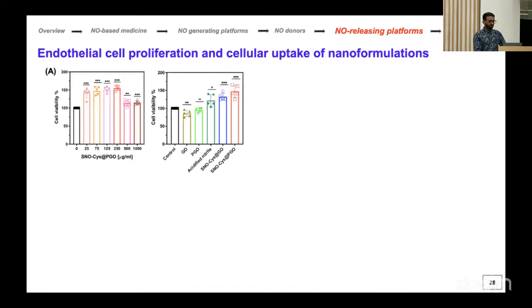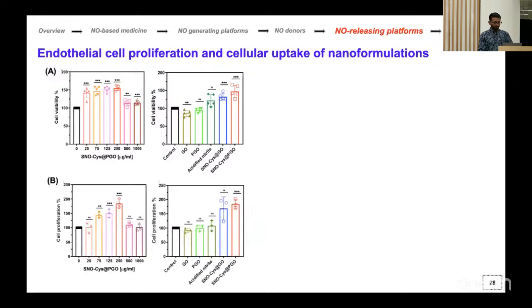And then we look at the endothelial cell proliferation, and we show that under different concentrations there is a higher proliferation of endothelial cells, because we want to improve the proliferation of endothelial cells so they can relax the blood vessels. We also compare it with unmodified graphene and with acidified nitrite on its own. They also improve the proliferation, especially acidified nitrite, but when we are carrying nitrite with graphene, of course we are carrying a higher amount, and in a controlled manner, so that gives a better proliferation. The first one was an MTT assay, and for figure B, because MTT assay is not really a proliferation assay, we use BrdU, a DNA proliferation assay, to show that this is definitely proliferation of cells. We got pretty much similar results.